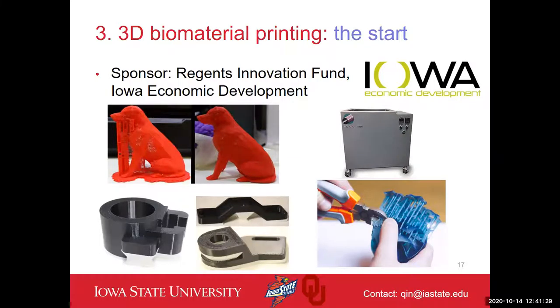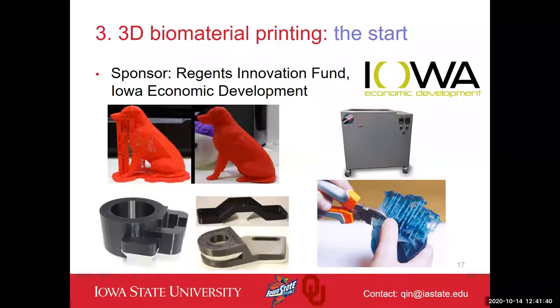If we are making a part layer by layer, and there is a hanging structure of the part, or there are inclined surfaces, usually we have to have the so-called supporting structure to ensure that we can still stack up the materials. For instance, over here, the white color of the bottom parts and the blue color supporting structures are all used to support the hanging over structures. Usually if the angle is more than 40 to 45 degrees, there has to be supporting structures to support the upper layer printing. That's the reality of extrusion-based 3D printing, or fused deposition modeling.